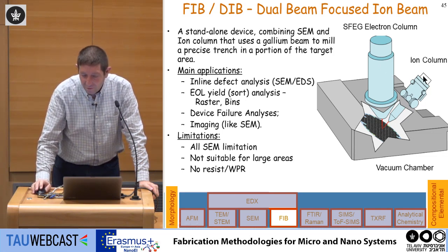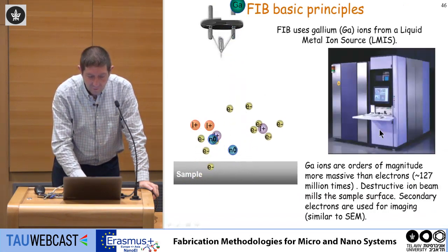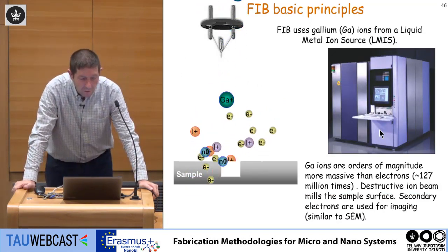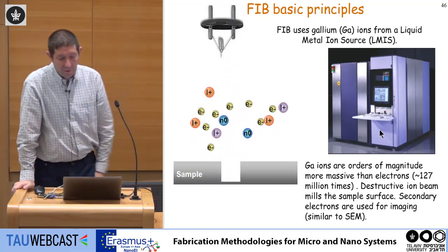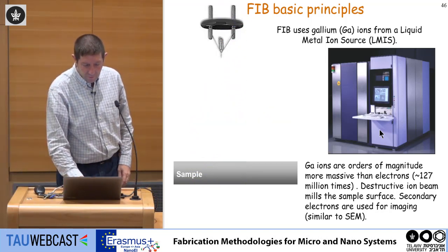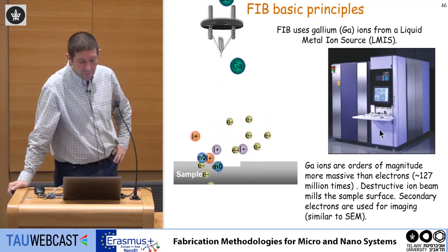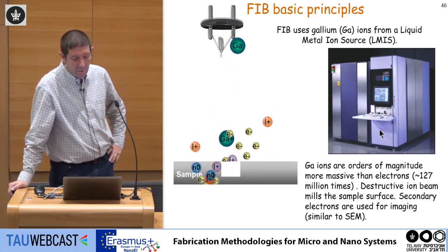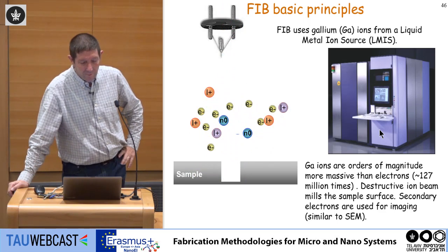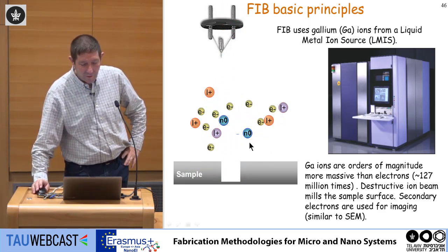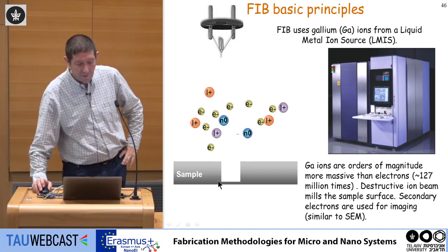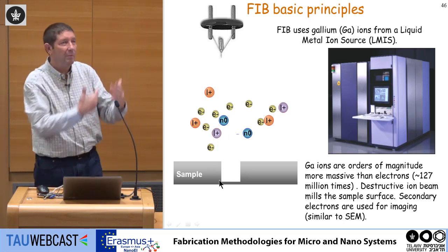And here you have the ion beam coming from this side, and the field emission gun coming from here. So you have one beam of electrons coming from here, one beam of ions coming from here, and you can cut an area and take a look at it. So this is the basic principle. The FIB uses gallium ions from a liquid metal ion source. Let me run it again. If you focus it on a certain point, you can sputter the material. If you sputter the material, you can cut the sample, and then if you look from here, you can see the side of the sample. So you can take an image from the side of the sample.